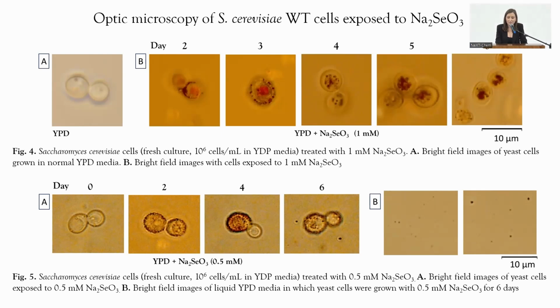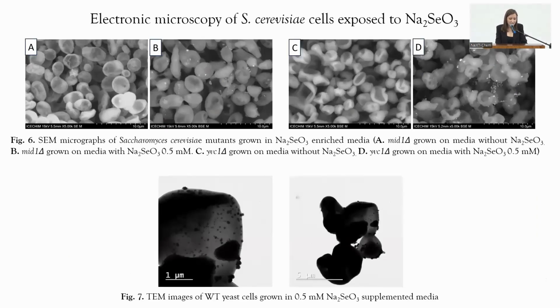In the second set of pictures, images B show the media in which yeast cells were grown, where selenium nanoparticles can be observed as well. So yeast cells can also synthesize external selenium nanoparticles. We have selected the most sensitive MID1 strain and the most resistant YVC1 strain to obtain some SEM micrographs. Scanning electron microscopy of this strain grown in media with and without selenite showed that in the presence of sodium selenite, as we have seen before, these cells indeed form selenium nanoparticles, which can be seen here in pictures B and D as those tiny white spots.